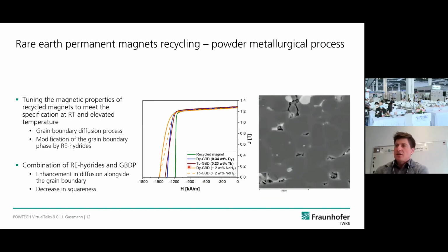Further, one can also use the well-known grain boundary diffusion process, for instance. In this case, the amount of heavies needed for getting a higher coercivity is less, since the heavy rare earths are just located at the grain boundary phase, and since it's a nucleation type magnet, it's a location where it's needed, and it's not needed in the middle of the grain. So with this technology, the magnet properties can be further tuned.